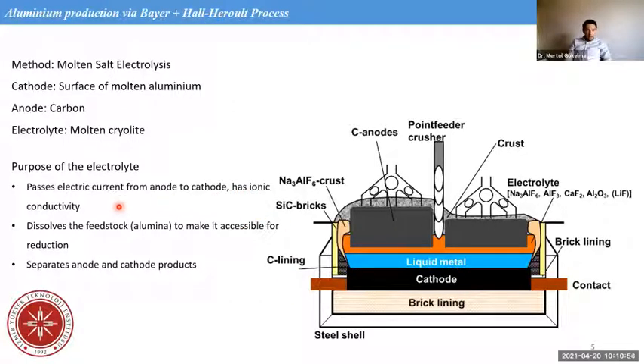And another reason we use this electrolyte is because it dissolves alumina. It is needed because alumina will not melt at this temperature. The temperature is approximately 1000 degrees, ideally 960-70 degrees Celsius. So alumina will not melt. The melting point of alumina is over 2000 degrees Celsius. That's why alumina has to dissolve. Alumina in this case is aluminium oxide. We call it alumina. So it dissolves the feedstock and separates the anode and cathode products. So the anode product is the gas actually, and the cathode product is the liquid aluminium.